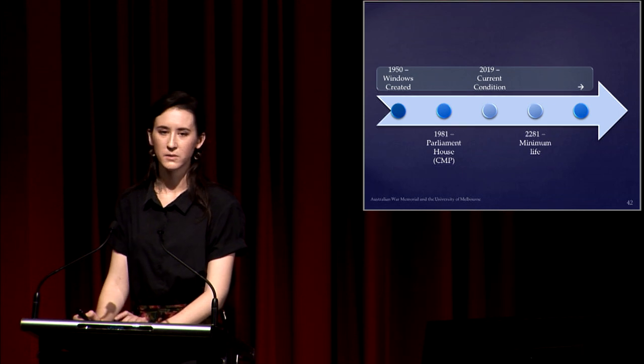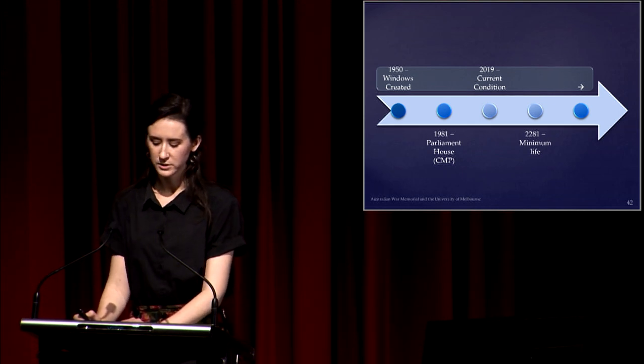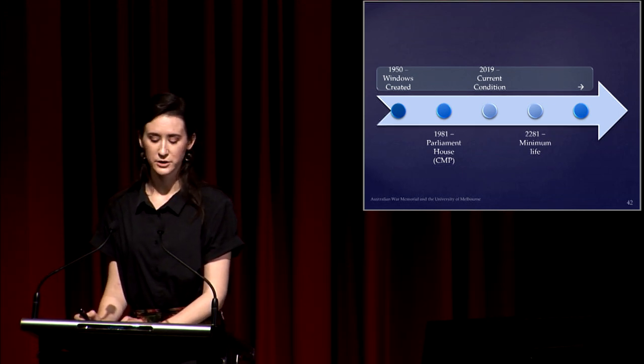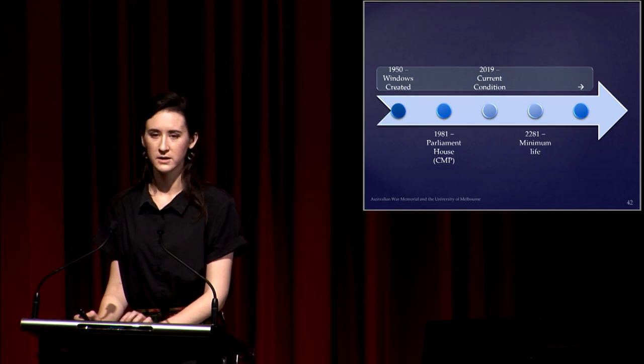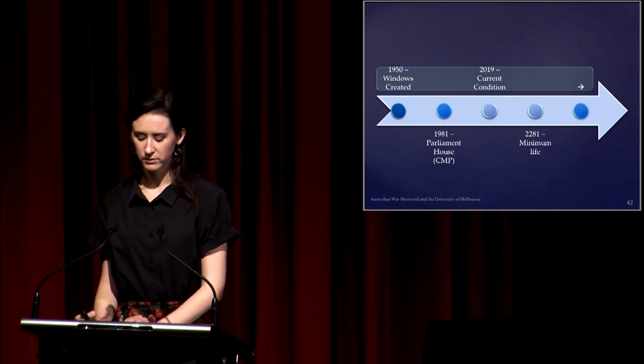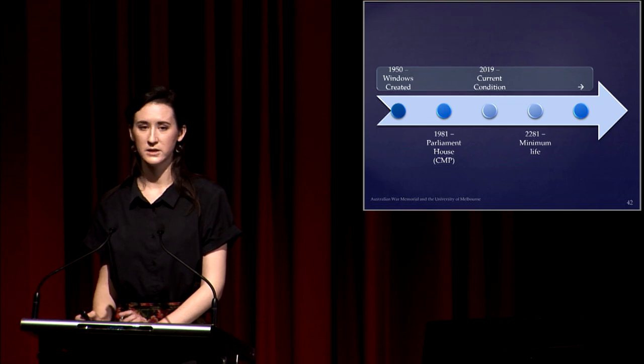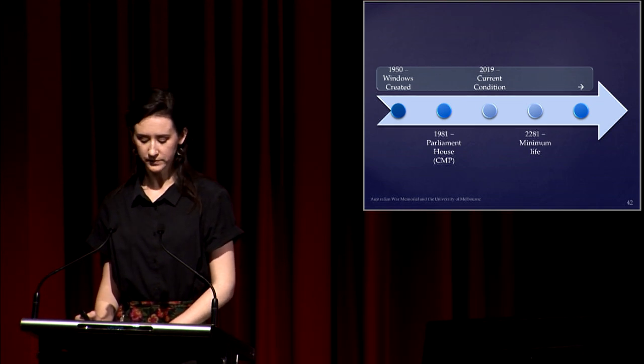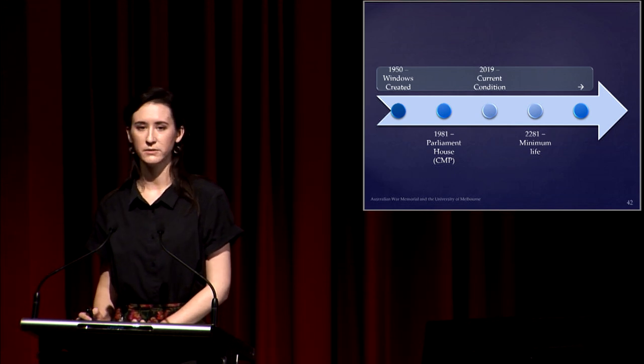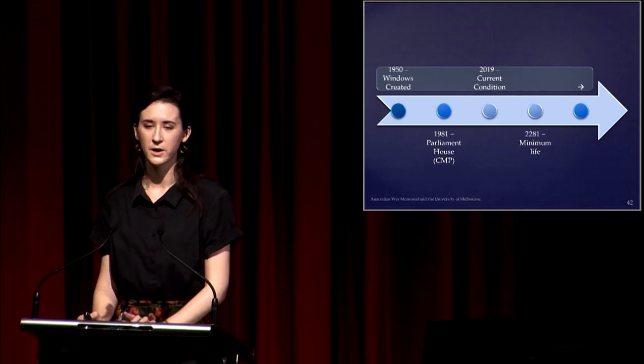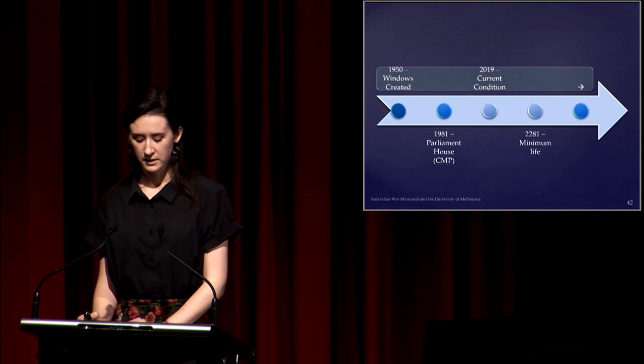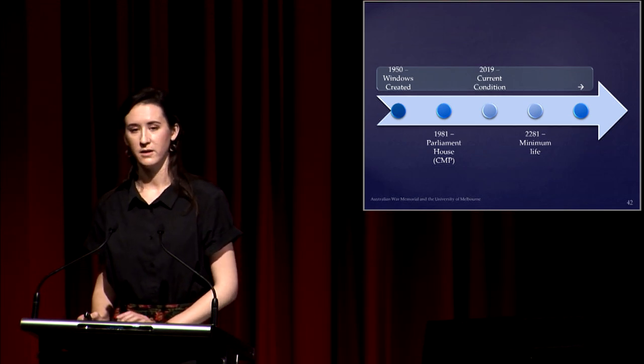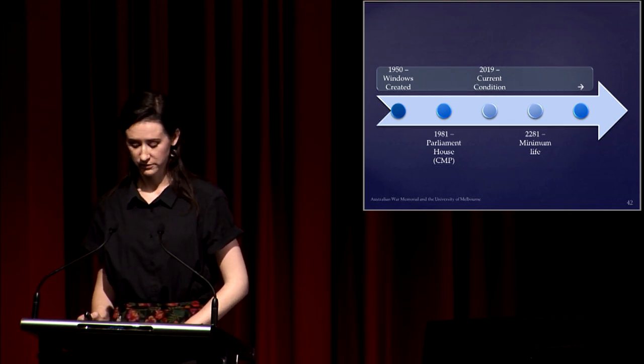However, this doesn't mean that we can be complacent, because we did identify active deterioration processes that must be monitored so that we can be sure that they don't become worse and cause significant damage in the future. We also need to be really careful of any unusual environments of dust and vibration that may be caused by the future redevelopment, and we need to ensure that there aren't any unmitigated effects from these issues.